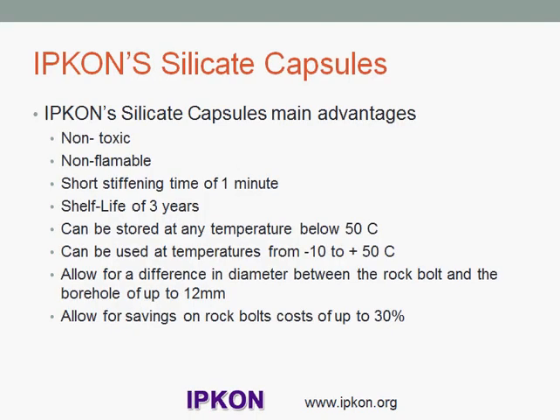Being non-toxic, the installation of silicate capsules does not require the evacuation of a mine to avoid intoxication by styrene vapors. The stiffening time of the mixture of the silicate capsules is only 1 minute. The shelf life of the capsules is 3 years. They can be stored at any temperature below 50 degrees Celsius. They allow for a difference in diameter between the rock bolt and the borehole of up to 12 millimeters, permitting savings on the cost of rock bolts of up to 30%.